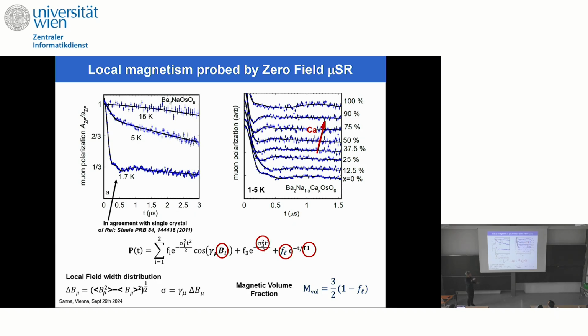Okay, you can see that the oscillations are not very clear, even in the sodium. But we see that at low temperature we have a magnetic state, because this signal is characteristic of a magnetic state, while in a non-magnetic state you have this signal.